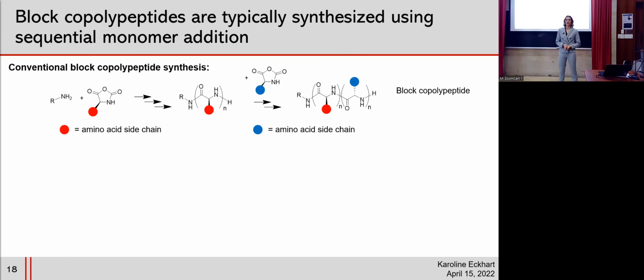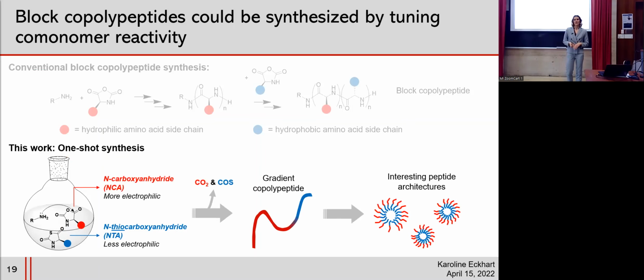And this is commonly used to make any kind of block copolymer or block copolypeptide. But we wanted to create a way to make this block copolypeptide synthesis more convenient. What if we could just add in all the monomers at once, set it and forget it, and come back the next day and have a peptide amphiphile? We wouldn't have to worry about catching this propagation right at the end and then adding in our second monomer at the precisely correct time. So we rationalized that we could create a copolypeptide polymerization system that is reliant on different reactivity of the monomers.